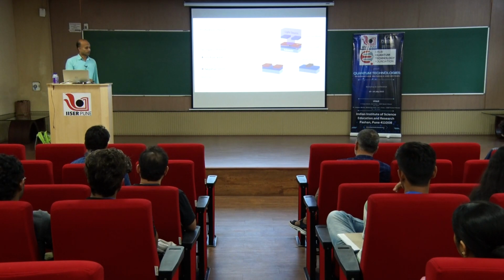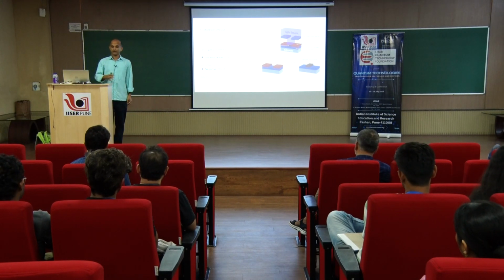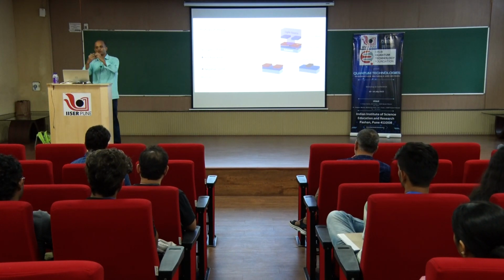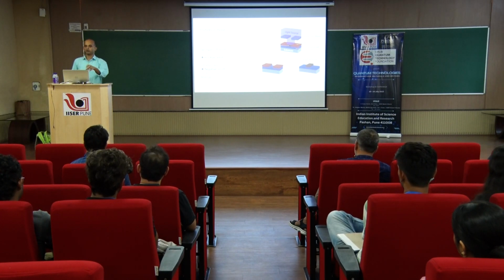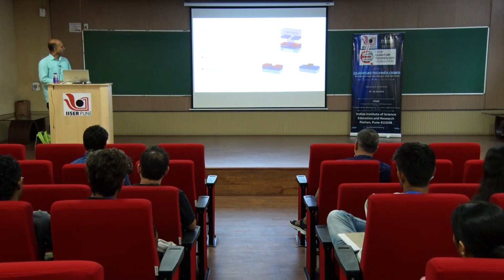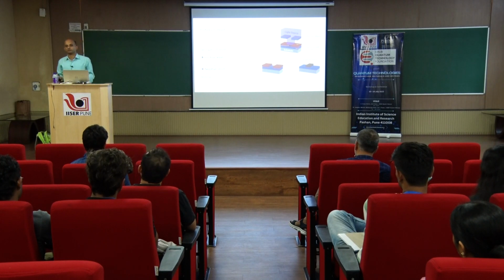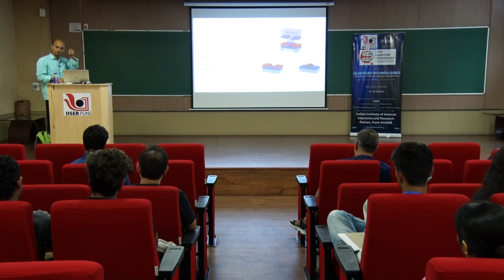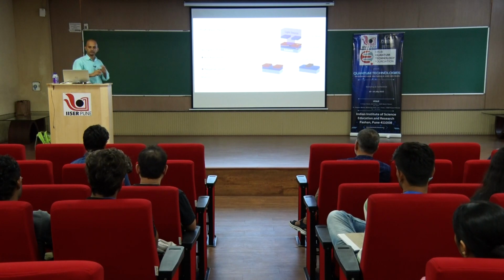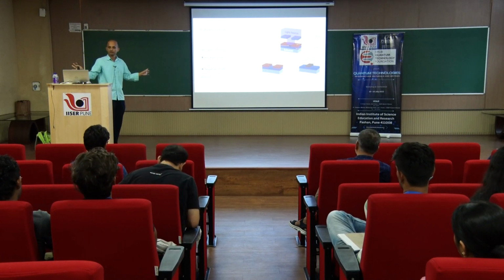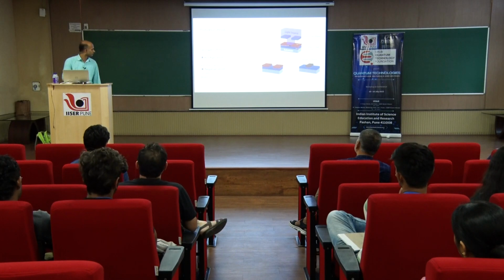part will go. Okay. Especially it is very useful when you want to etch, say you got a monolayer graphene, okay, on a very small area, and you want to etch rest of the thing. So you want the resist to stay there to protect the monolayer part, and you want everything to get washed clean. So if you do RIE, you have to use this negative photoresist. You just protect that part, because if you want to use positive photoresist, then you have to expose the entire chip, which is very difficult. Okay. But in this case, you just expose that small part, it will get hardened, and then you wash it and do RIE to clean unwanted portion from it.